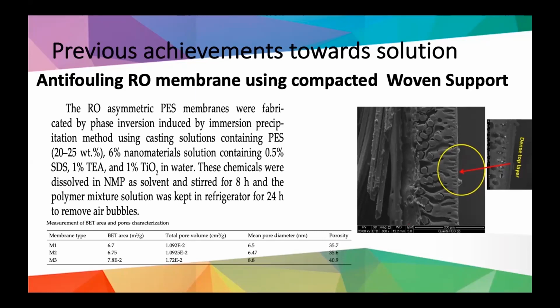So you can see clearly the prepared membranes. M1 is the membrane when casted over the glass without any support. M2 is the non-woven, where we cast the membranes over a non-woven fabric support, which has a certain characterization. Then we can see M3, which is the woven support. The woven support has this structure here. You can see in the scanning electron microscope morphology a neat, thin film layer for these membranes.